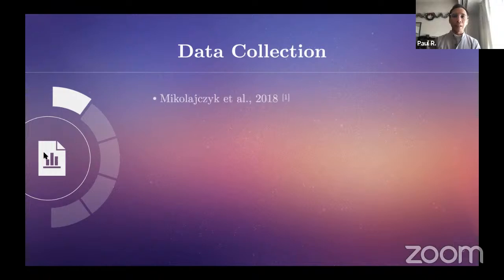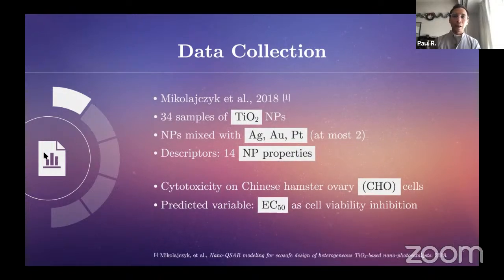The first step is data collection. We used the data samples by Mikolajczyk et al., where in their study, they produced 34 titanium dioxide nanoparticles mixed with various concentrations of at most 2 metals via microemulsion. These metal NPs are silver, gold, and platinum. Each sample has 14 descriptors or features, and each one is tested for cytotoxicity on Chinese hamster ovary cells. They used the half maximal effective concentration or EC50 value as the predicted variable.